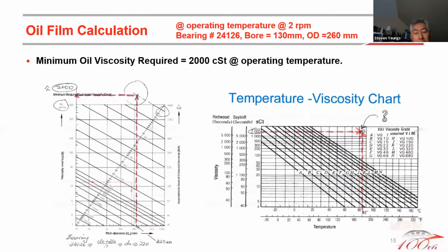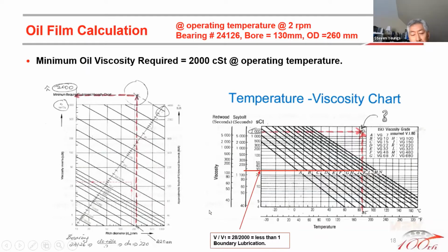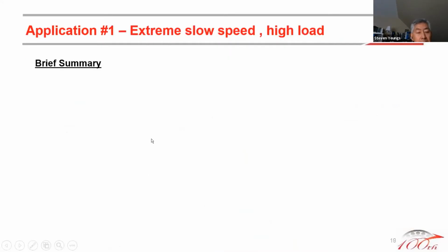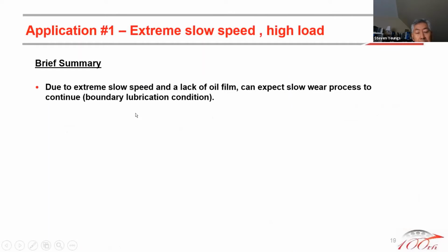And sometimes even if you want to provide something with adequate oil film conditions, maybe there are cases that you just cannot, mainly because the speed is such a low speed. So when you do that viscosity ratio, you basically have less than 1, so you're in a boundary lubrication condition right from the get-go. So as a summary, due to extreme slow speed and a lack of oil film, one can expect the wear process to continue right from the get-go.